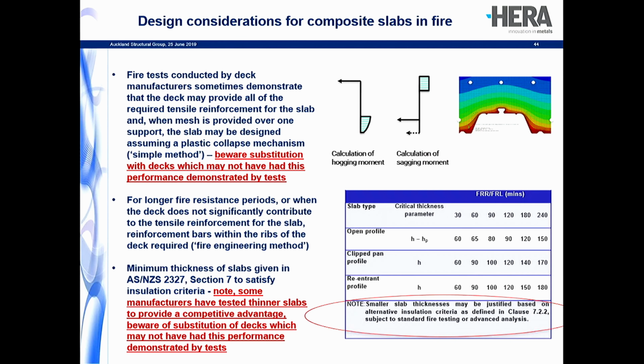The thing to watch though for these ones is that a lot of these tests are sometimes used to give manufacturers a bit of a competitive advantage. Some manufacturers have found that because they've got such good bonds between the concrete and the steel sheeting, they can actually use the steel sheeting in fire conditions to still reinforce the slab in sagging conditions. So one thing to watch for is that if there's ever a substitution, you have to be very careful that the deck or the manufacturer you're substituting to has done similar fire tests. Otherwise, you may well have to include bars within the ribs of the sheeting.